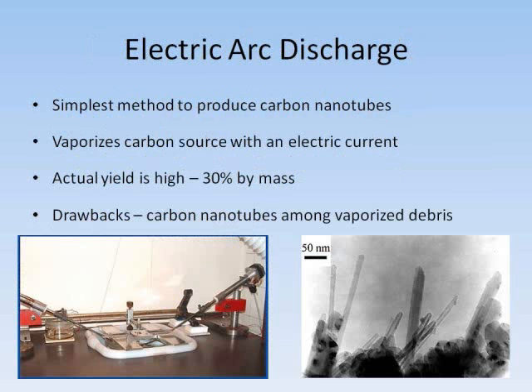The first method I will discuss is the electric arc discharge method. The synthesis of carbon nanotubes using this method is far simpler than the other two methods. This method implements two graphite electrodes — graphite being made solely of thin layers of carbon. The electrodes are contained in the presence of an inert gas. An electric current is run through the electrodes, ranging from 50 to 100 amps. The carbon of one electrode is vaporized, and a deposit is produced on the other electrode in the form of a rod. The yield is potentially high, depending on the temperature of the electric discharge.